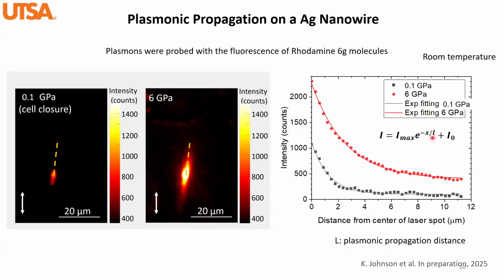But what we really care about is this L here, that is the plasmonic propagation distance. Here I sub 0 is the intensity that we detected at the background, because there may be some scattering inside the cell contributing to some intensity on the background. And here I max is the maximum intensity, at the laser spot center. So by plotting this, we were able to determine the propagation distance.